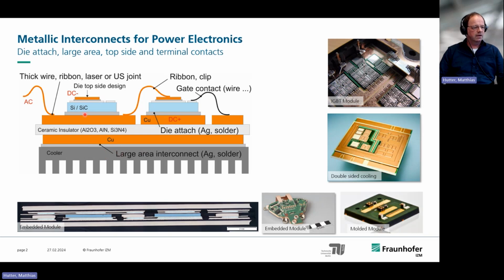So we have a die attach, we have a top side contact, we have a large area contact, we have wire bonds for the gate, and also maybe wire bonds for the current, but not only wire bonds, also ribbon bonds, clips, and also then for the AC contacts here, we have, for example, laser joints or ultrasonic joints.